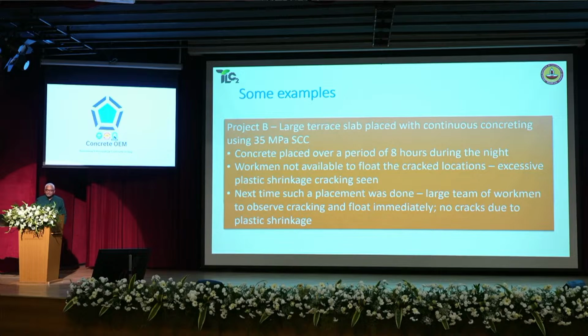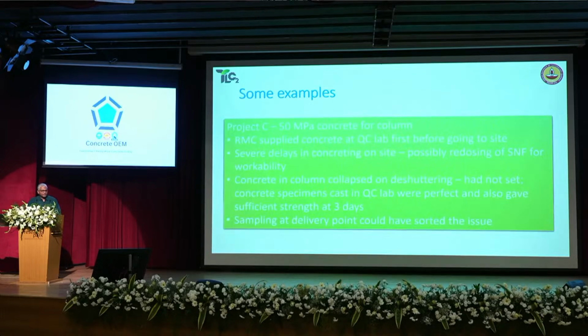So again, next time this placement was done for the higher floor, the terrace of the next floor, the slab for the next floor, there was a large team of workmen to observe cracking and float immediately. Absolutely no cracking was there. This was all self-compacting concrete. And no cracking was there when these workmen were there on the site to ensure that they could do the floating when the cracks appeared. And this is very early, during first couple of hours after placement, that you start seeing these cracks.